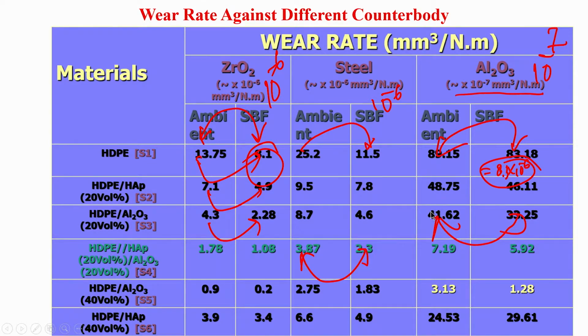So like friction coefficient, there is also a systematic reduction in the wear rate against each of the counterbodies when tested in simulated body fluid environment compared to tests carried out in ambient conditions.